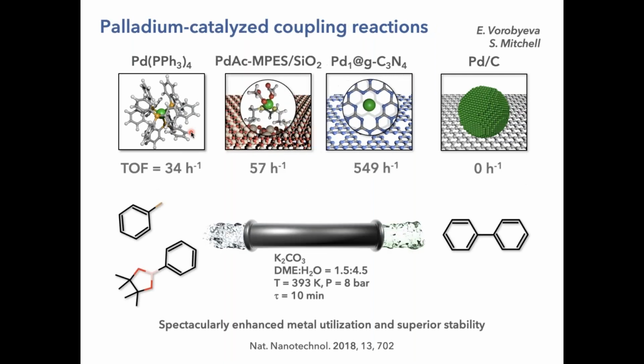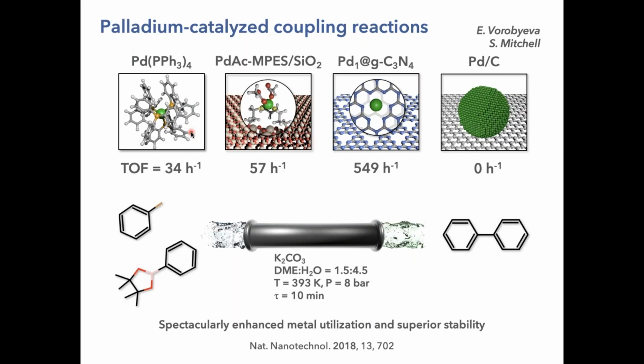And so that enables us to exploit chemistries that go in the direction of replacing homogeneous catalyst by heterogeneous single atom catalyst, which certainly lead to sustainability in the sense of improving catalyst separation in pharmaceutical applications or fine chemical applications. Here's an example of the flow Suzuki coupling, a classical reaction to produce biphenyls used extensively in industry, where we have compared the single atom catalyst with the state-of-the-art commercially used triphosphine homogeneous system, and we are able to get much higher turnover frequencies and much more stability. That's the most important thing, due to the characteristics of the system.